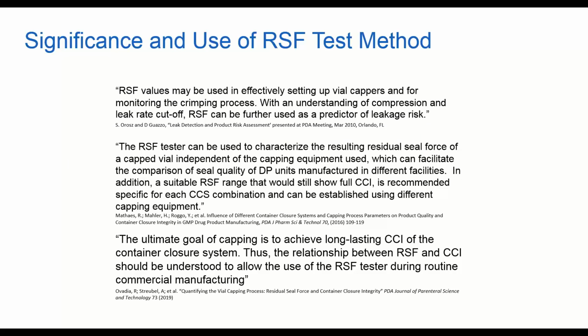So a lot of work has been done, especially in the last few years, going back 10 years ago. S. Orosz and D. Guazzo, he was with IMCLON at the time. They demonstrated that RSF values may be used effectively in setting up the vial cappers, as I'd mentioned, and monitoring the crimping process. With an understanding of compression and leak rate cutoff, which we talked about, RSF can further be used as a predictor of leakage risk. I want to emphasize here that it is a predictor of risk. It's not something that you can measure a vial's residual seal force and say this vial will leak and this vial won't. It cannot do that. It's not a leak test itself.